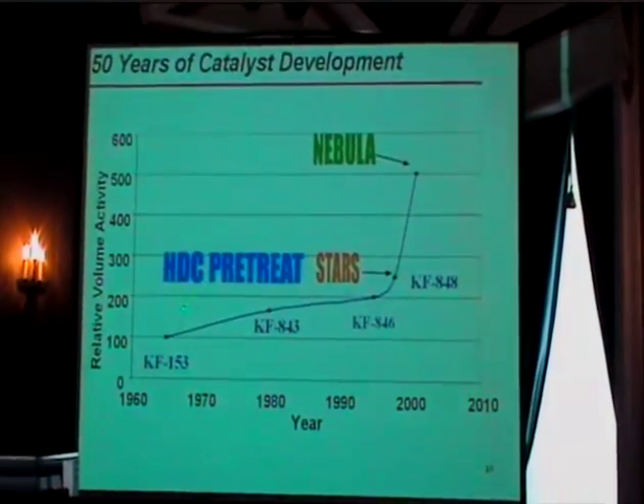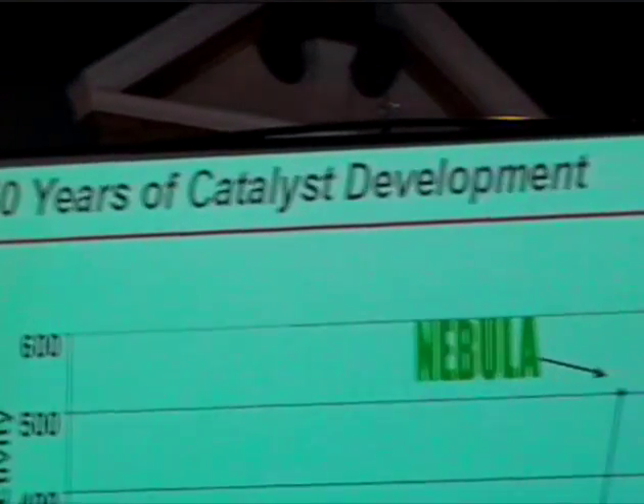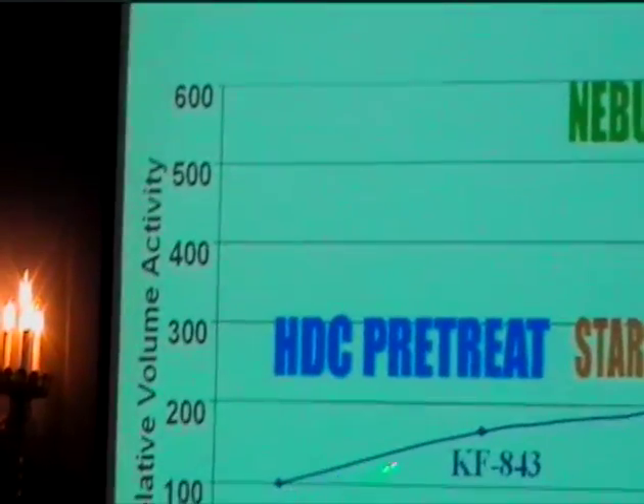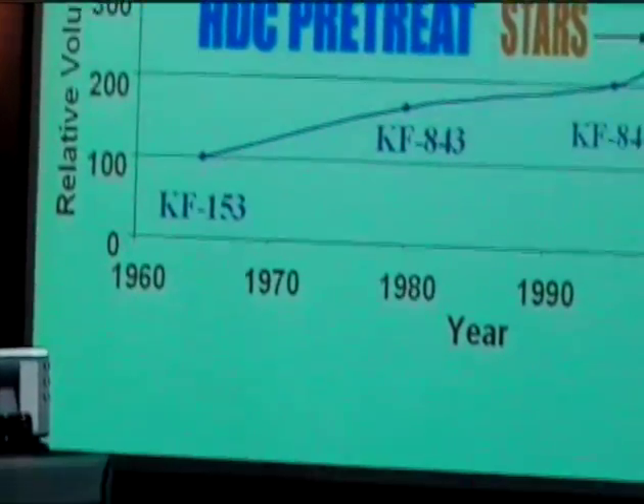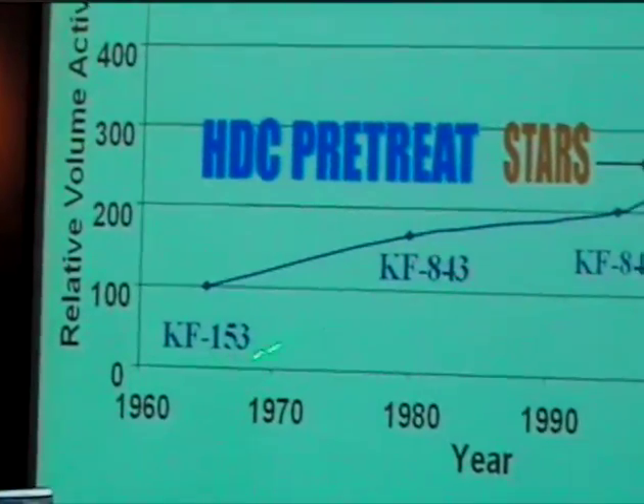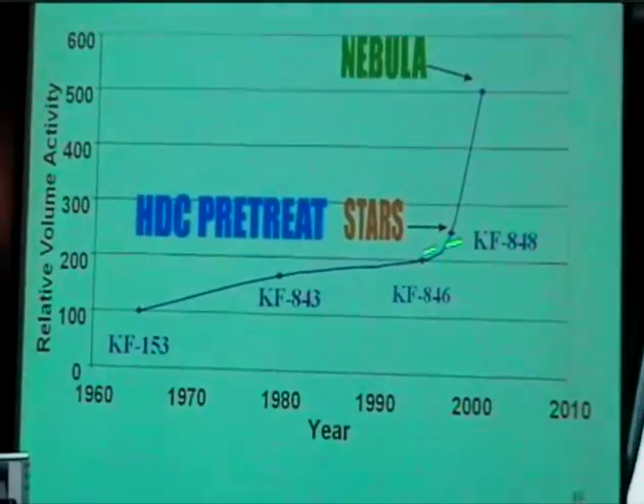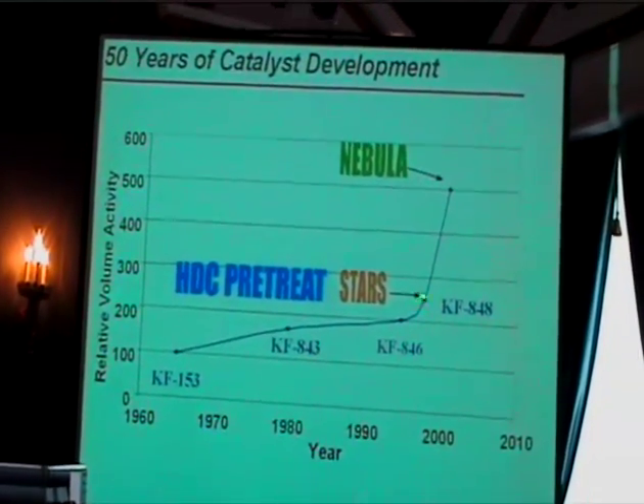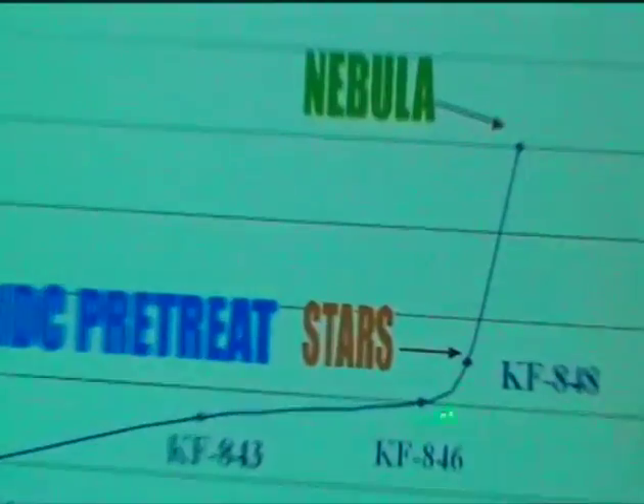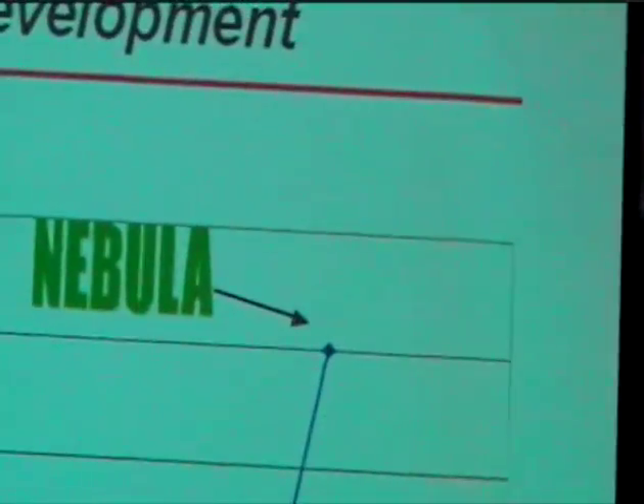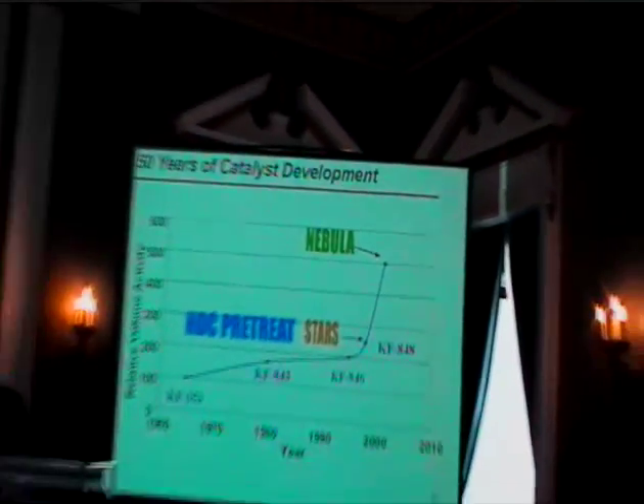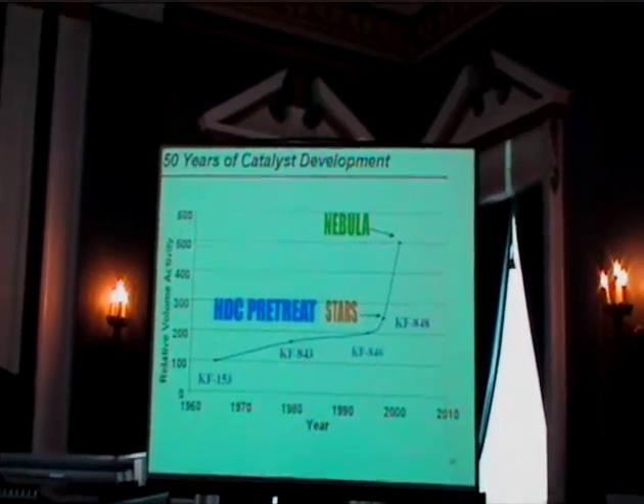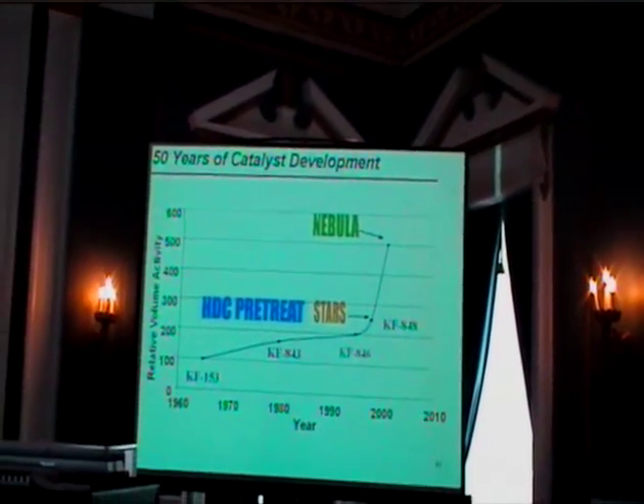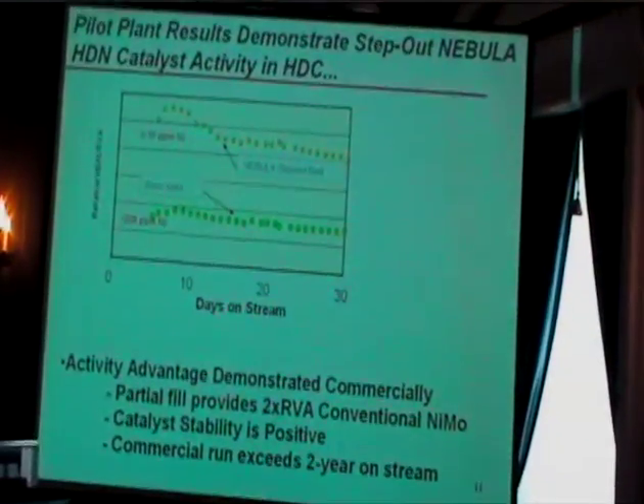Here's an example in hydrotreating, hydrocracking pretreatment using an LCO, light cat cycle oil feed. This is a little bit of a marketing picture, but it is in fact what happened. These are a bunch of the supported catalysts that Albemarle or Akzo had done. This is their so-called STARS catalyst, which had a nice improvement over where they were before that. And here's where Nebula was. So we're getting about a factor of two improvement in volumetric activity for this catalyst for hydrocracking pretreatment. And it has been used in several refineries before this.